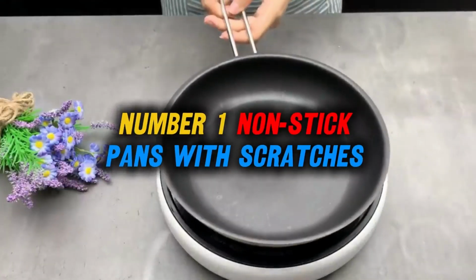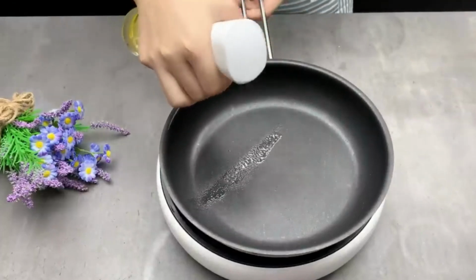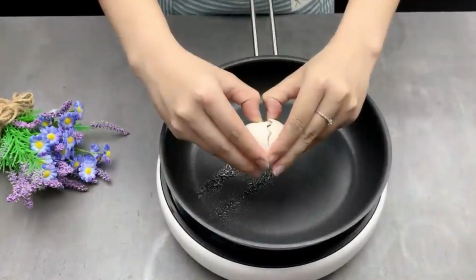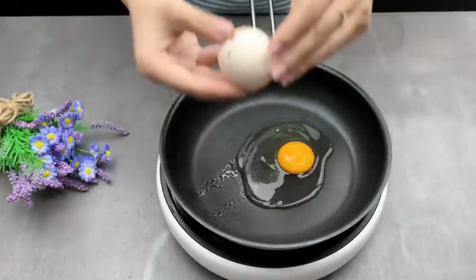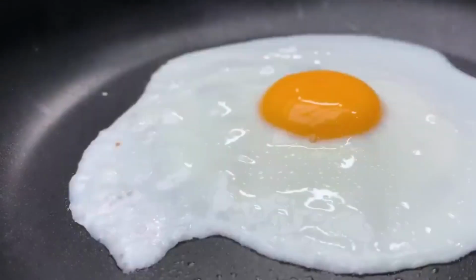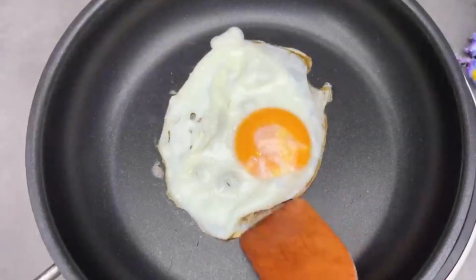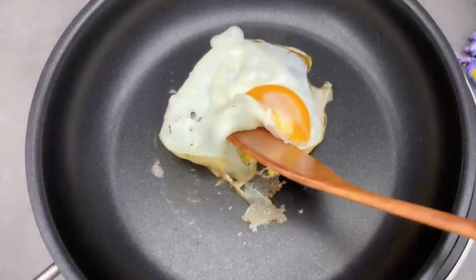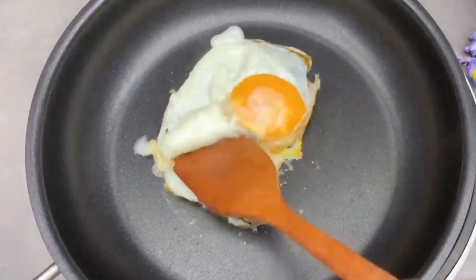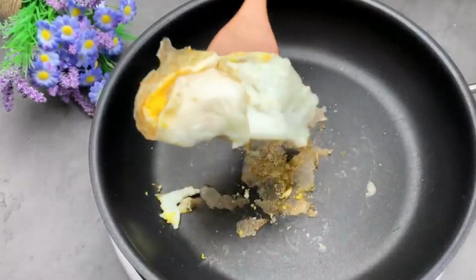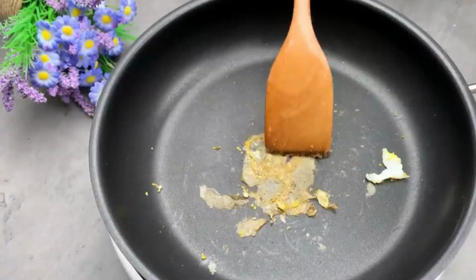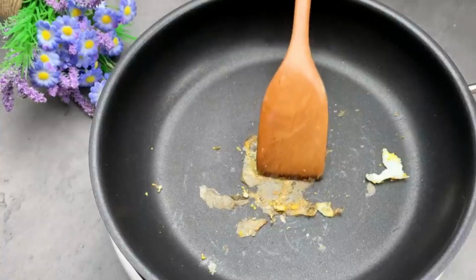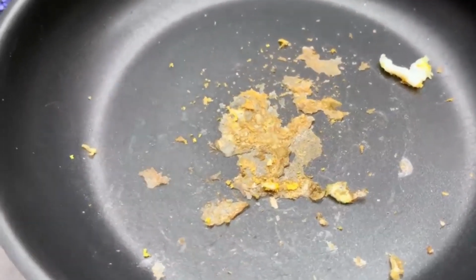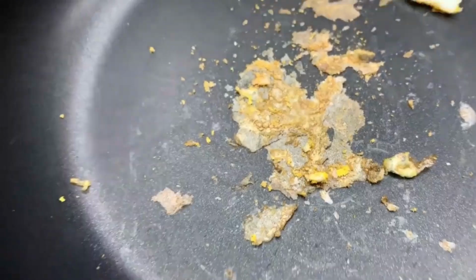Number 1. Non-stick pans with scratches. Teflon/PTFE. That silky egg slide feels safe, but one scratch turns a stable film into a weak spot, and heat does the rest. Here's the truth. PTFE holds up at normal temps, then breaks down when you push it hot or damage it. A nick exposes layers, speeds wear, and under high heat, the coating can give off fumes and shed bits.